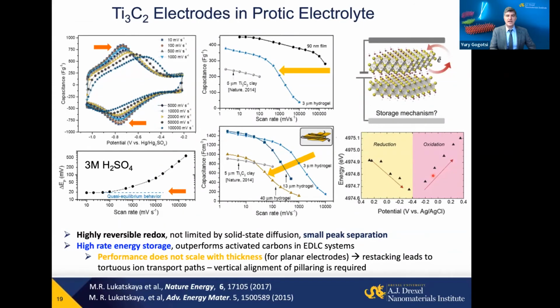We can store charge electrochemically in redox processes. And if you look at the cyclic voltammogram, what we can find, there is an overlap of double layer capacitance with a broad but electrochemically reversible redox peak, because the separation between reduction and oxidation peaks is very small, just about 20 millivolt here. What is interesting, the peak stays even if the scan rate increases up to an enormous rate of 100 volts per second. So we charge our device within, say, 10 milliseconds, and we still have redox.